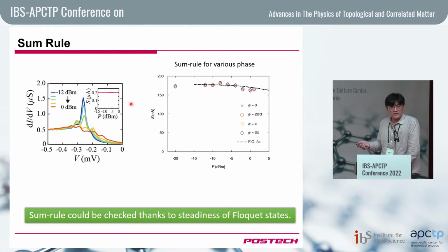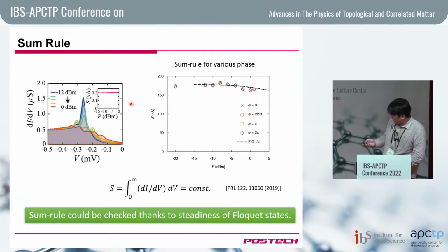Sum rule. So we integrated the dI/dV curve as a function of voltage, and that is basically the area of this dI/dV curve. As we change the power of the microwave, we just plot the area of this dI/dV curve. That is almost constant, except there's a slight decrease as power increases, and we think that is just due to the fact that our voltage integration is done within a finite voltage range. Okay, so we didn't measure the voltage spectrum higher than 0.5 millivolts.